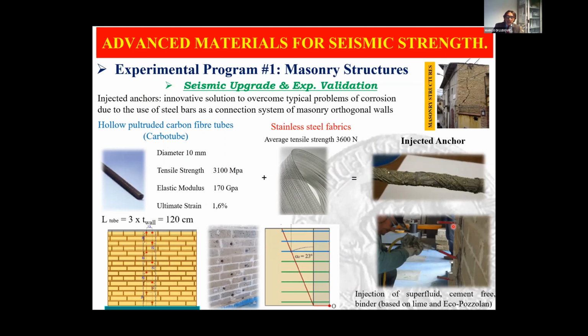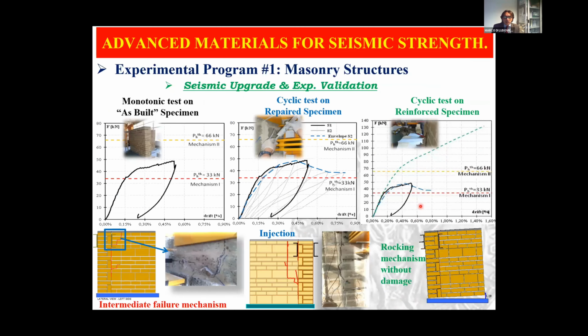And these are the laboratory phases. Also important is that the injection was done by using a cement-free binder, so based on lime and Eco-Pozzolan. And this is good for historical building applications. So here you can see the comparison. This is what happened before the strengthening solution, and this is the behavior after the strengthening solution. So the grey line is that related to the strengthened